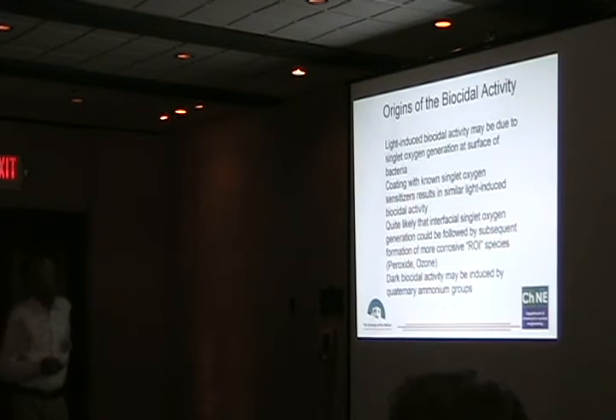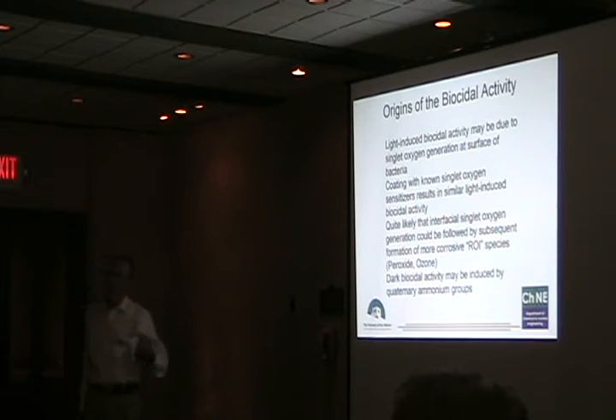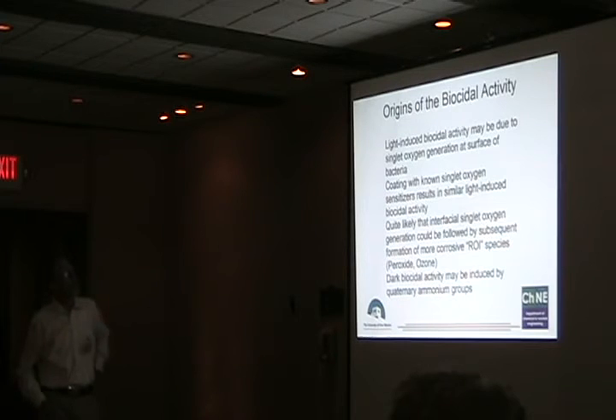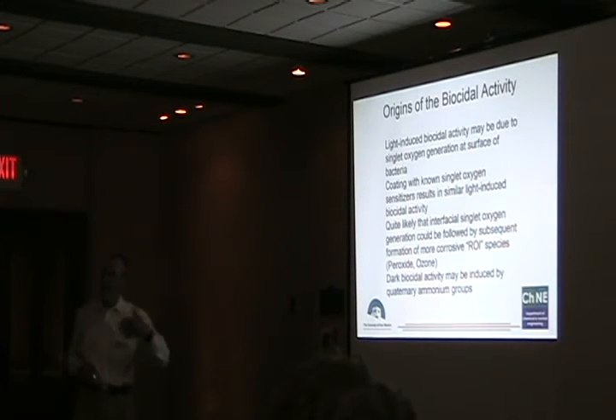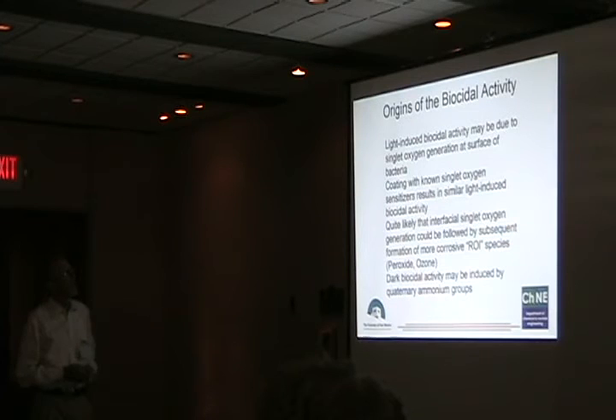So we've looked at this in a qualitative fashion, and we think that the origin of biocidal activity may be due to singlet oxygen generation at the surface of bacteria. We know that generating singlet oxygen from the polymer by the beads or polymer itself would not result in any killing of bacteria due to the fact that the lifetime of singlet oxygen and the rate it could travel are not sufficient to deactivate or to counter the bacterium and kill it. We find if we coat, for example, microspheres with known singlet oxygen sensitizers, we get very similar biocidal activity.